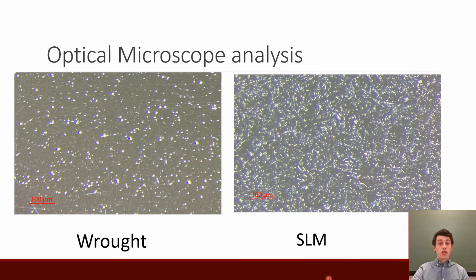Another important consideration is the distribution of them. On the selective laser melting side, we see these are much more tightly packed and kind of formed in little groups. Comparing it over to the wrought sample again, we see that they're very evenly distributed and there seems to be no such patterns present. Confirmation that there are far more niobium carbide particles in the selective laser melted sample, as well as them behaving so differently, provides strong evidence that this is a key reason for the difference in behavior at high temperatures.